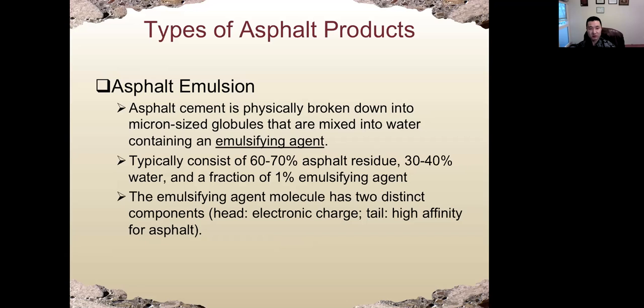The third type is asphalt emulsion. Asphalt cement for asphalt emulsion is physically broken down into smaller size globules. That will be mixed with water. The water has a small percentage of so-called emulsifier agent. The percentage of emulsifier agent is very small, only about 1% of total. So for asphalt emulsion, we have 60 to 70% of asphalt residue, about 30 to 40% of water, and 1% of emulsifier agent. Emulsifier agent is similar to chemical admixtures, such as superplasticizer we use in Portland cement concrete.